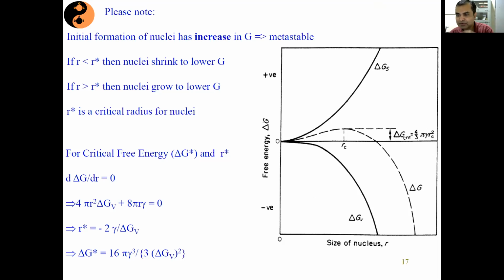The simplest answer is, if you just take the example of R equals 0.2, some arbitrary unit. So 0.2 square is 0.04, but 0.2 cube is 0.008, right? So that's why I'm saying that for a smaller radius, your delta GS is way beyond your delta GV. But if you take R equals 2, then R square is 4 and R cube is 8. So now delta GV has dominated. Okay. So for higher radius, it's delta GV which will dominate, whereas for a smaller radius, it's delta GS which will dominate. That means surface energy will dominate over the volume energy for a smaller radius of nucleation. So you can see that as long as your nucleation radius is below RC, it's delta GS, that means surface energy is dominating over the volume energy.